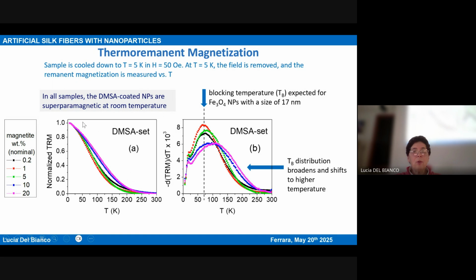But there is also something more that you can do, because if you take the derivative of this curve, of course, you obtain other curves which show a peak. And the whole curve is a figure, let's say, of the distribution of blocking temperature in your assembly of nanoparticles which are embedded into the fiber. And the maximum is the mean blocking temperature. And here we obtain very satisfactory results, because in the fiber with the lowest concentration of magnetite, the peak was exactly where we expected, considering magnetite nanoparticles with the size of 17 nanometer, which was the mean size of our distribution. So this means that the particles were well dispersed into the body of the fiber.